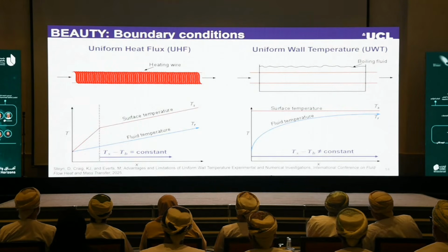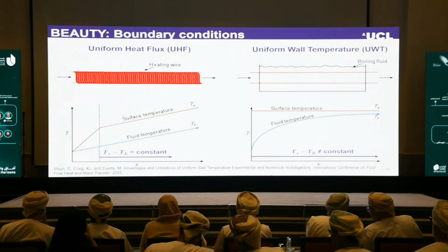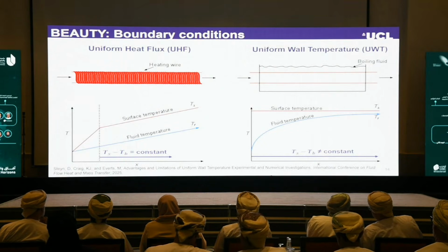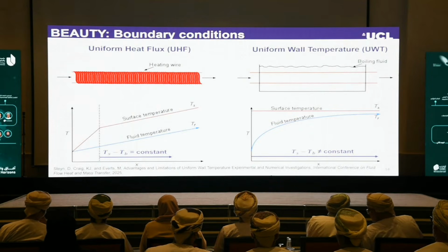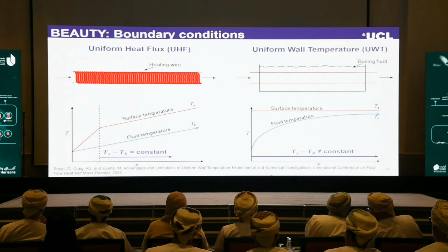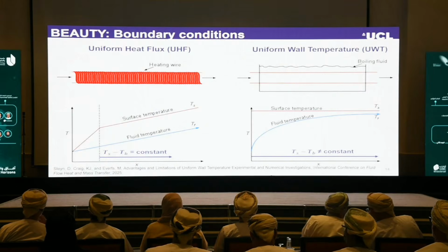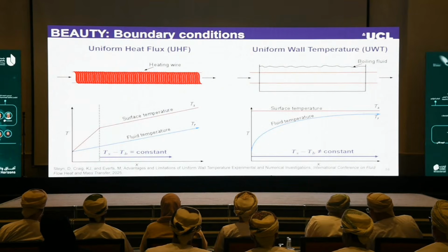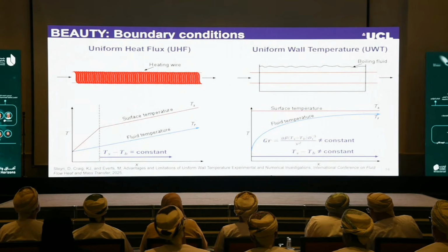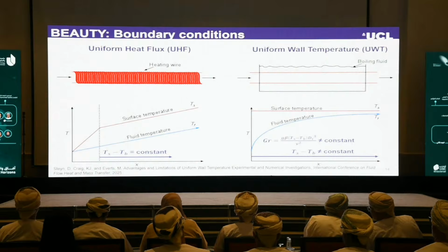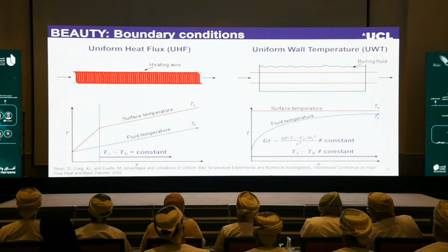However, when we change the boundary condition to a uniform wall temperature boundary condition, and this is actually typically the boundary condition we deal with in most phase change heat exchangers, because the moment it involves boiling and condensation, we're dealing with this kind of temperature profile. We can see that this surface fluid temperature difference is almost never constant. And because that is not constant, our Grashof number can't be constant, and it tells us that our mixed convective behavior is continuously changing inside the heat exchanger, and we need to know how we can benefit from it in order to improve our heat exchanger performance.